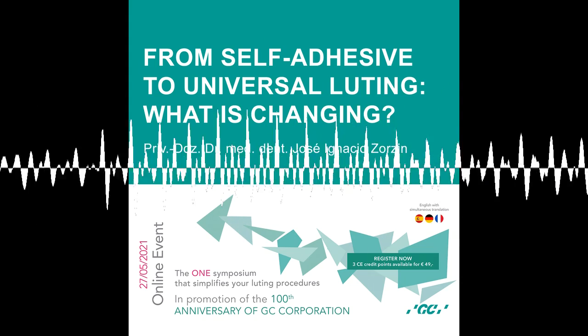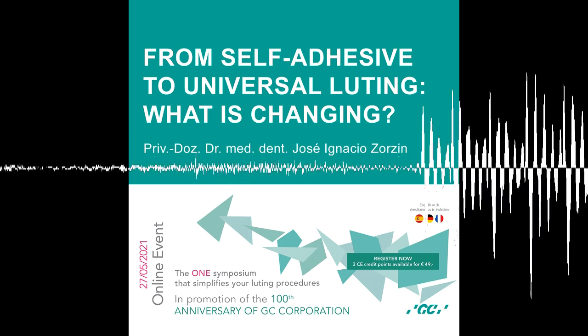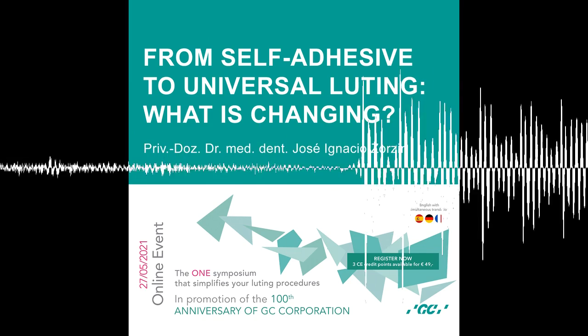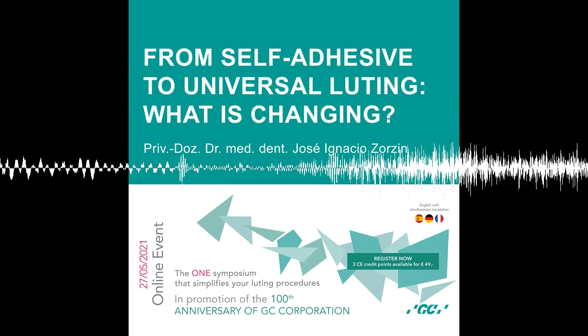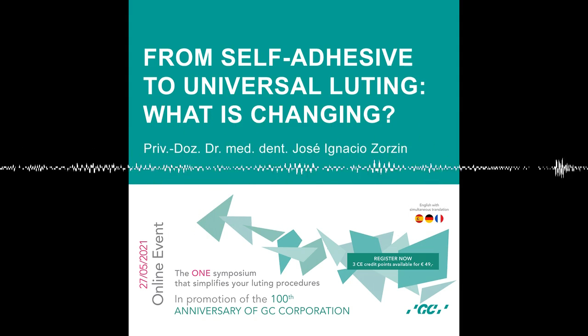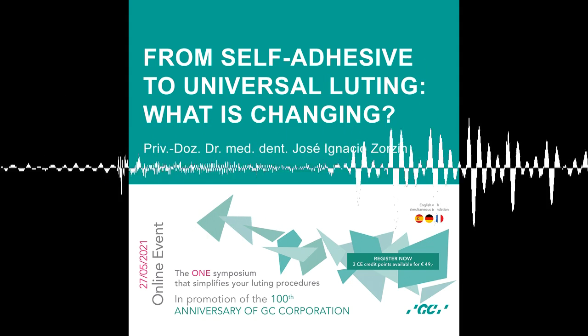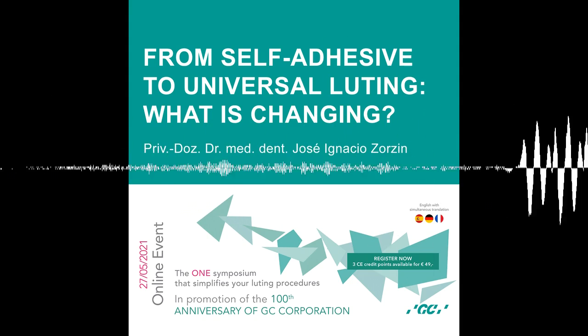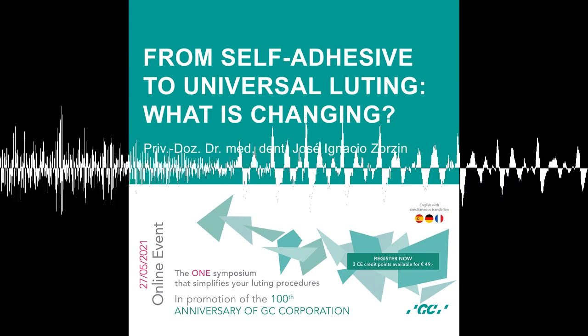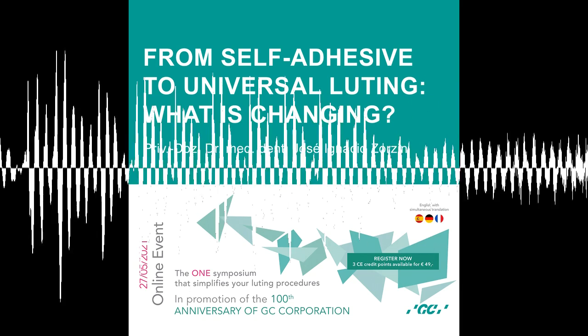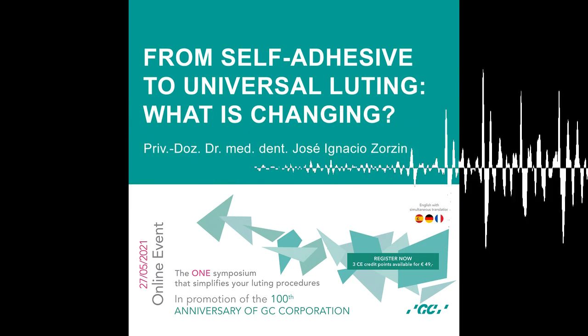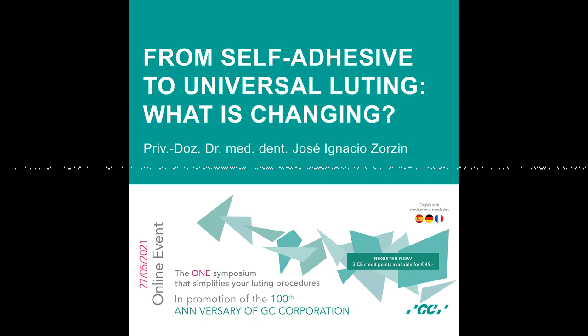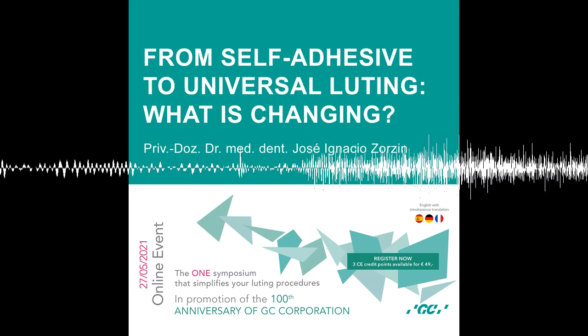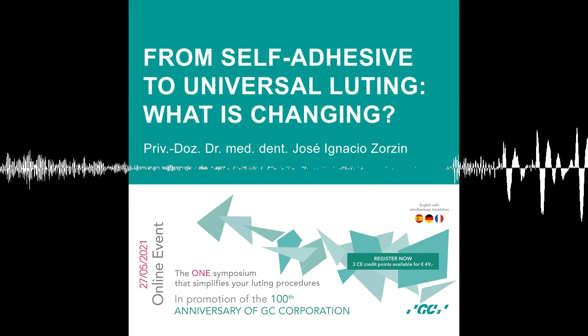Are you a fan of the tack cure possibility, or do you remove the excess cement somehow differently? Tack cure technique, for example when doing a crown, it's fine. It's really a possibility to manage the excess and do the excess removal. I use it when doing crowns. For example, when luting glass ceramic crowns, I do a lot of tack cure. It's fine for cleaning, and also you don't have the oxygen inhibition layer. As you take off the excess, the resin gap is polymerized at a relatively higher level, so you won't have that extent of oxygen inhibition layer as if you would do it the other way around.